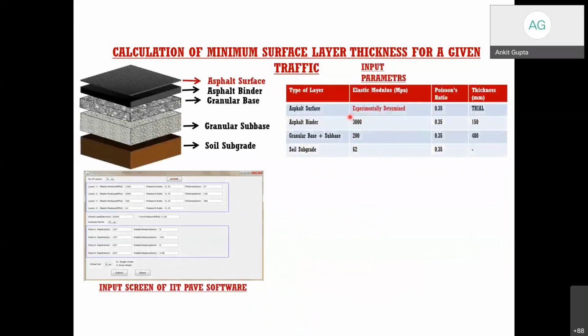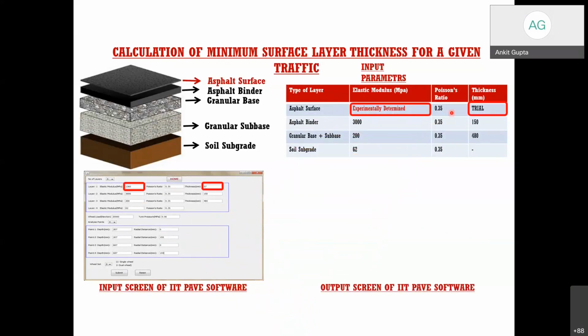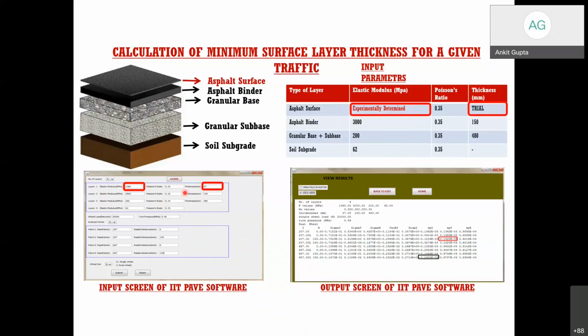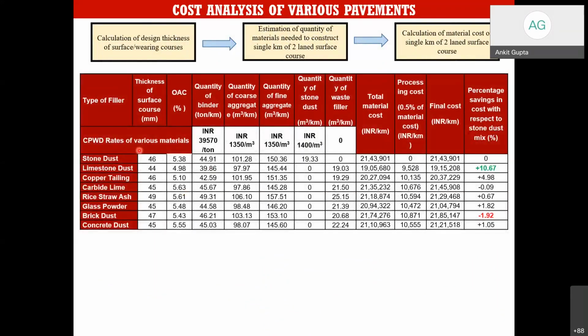Now only for the surface layer, that is the surface course, the resilient modulus values which we have got from our laboratory experiments, we have used those elastic modulus values. And with respect to that, we have given the different trial thickness for the different waste modified mixes. Okay. So we could design our pavements with the different values of the layer thicknesses. This is the thickness of the surface course, considering the binder course, the base and the sub base course, and the subgrade as constant. We have not touched the thickness of those layers. We have not touched the properties of those layers.